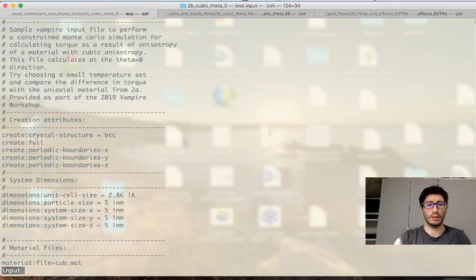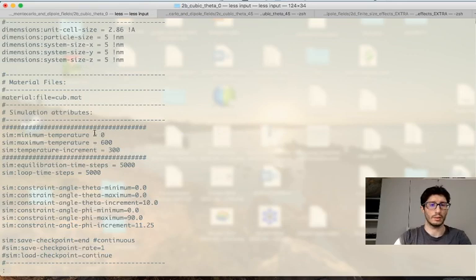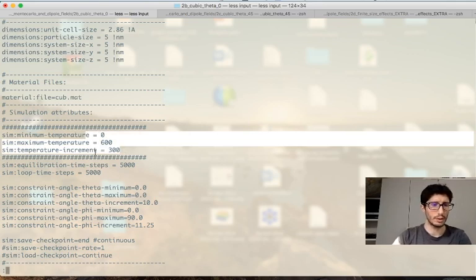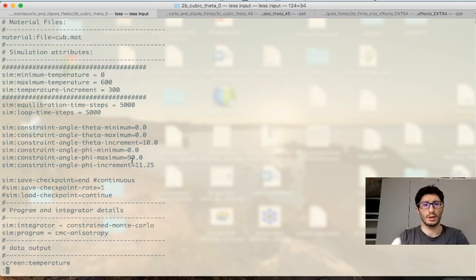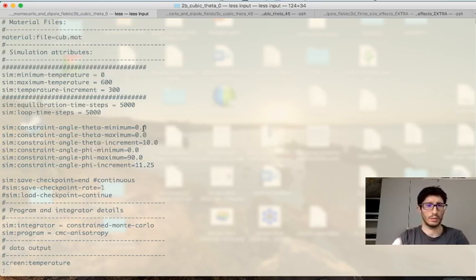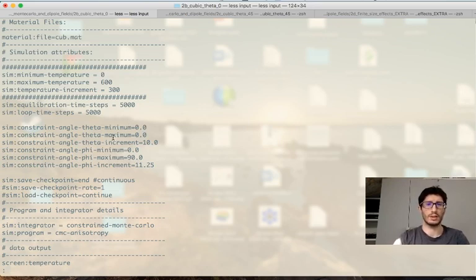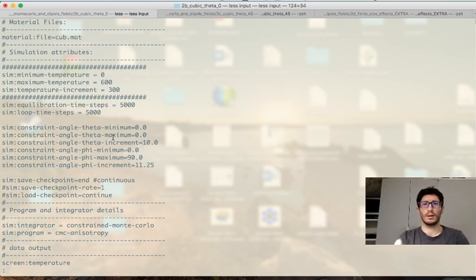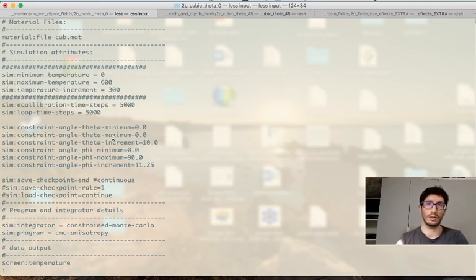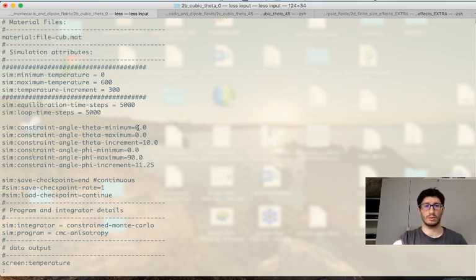And in our input file the other thing I did to run it with respect to the one you would find in the directory is to set the parameters for the temperature range. So I said to go from 0 to 600 with step of 300 so that we will just get three temperatures. And I left the angle settings as you will find them. So in this case also the directory suggests we will explore the torque along the theta 0 direction. And I do specify this because in a cubic material we have now all these equivalent directions the profile of the torque and so the free energy will depend also on the rotation angle.